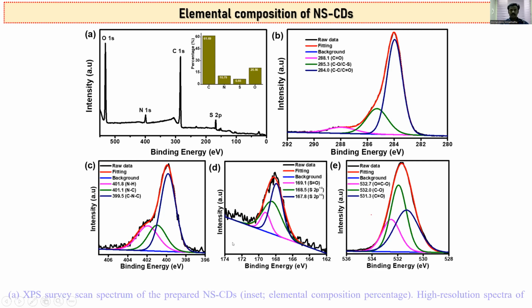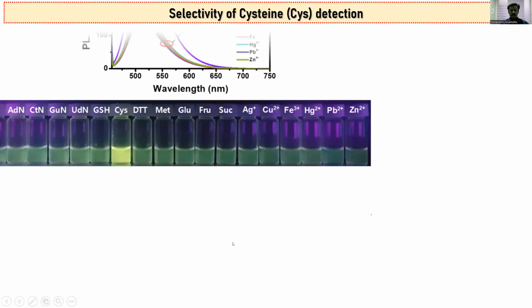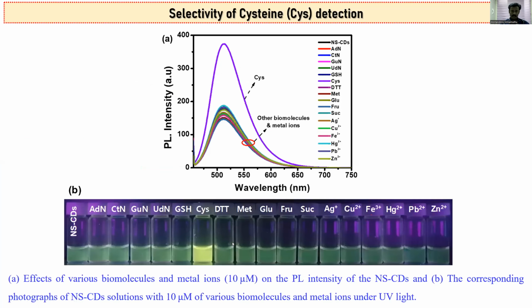The next one is the selectivity of cysteine detection. For the effect of various biomolecules, we used a maximum of 10 micromolar for the photoluminescence studies. Here I tested different nucleoside molecules, adenosine, cytosine, guanosine and other molecules, and also important metal ions, cations. I used a final concentration of 10 micromolar. Then we get the photoluminescence spectrum, with a significant enhancement by cysteine over the biothiols. We used 4 different biothiols with different functional groups: glutathione, cysteine, DTT and methionine.